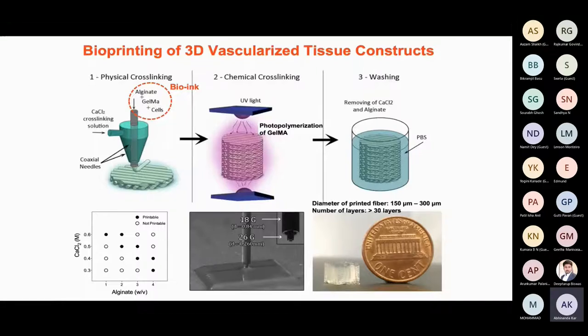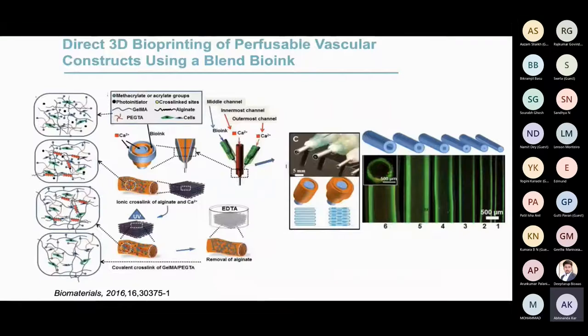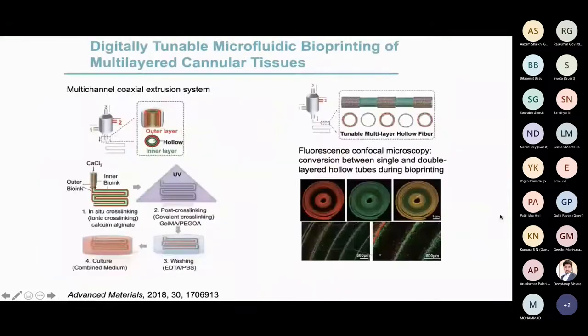Now, just to continue on about some of the other ways you can combine these different inks, here you can see another example of bioprinting that is alginate based, but the alginate and the material here is in the shape of coaxial nozzles. So as you're printing, you can actually print things that are in the shape of tubes. So not just rods, but also tubes. And this can be used to make structures that start looking like blood vessels. You can also do other types of things with this multi-nozzle structure. So you can actually print multiple types of layers and build these prints on top of different structures. And then we can actually start pushing these things forward.